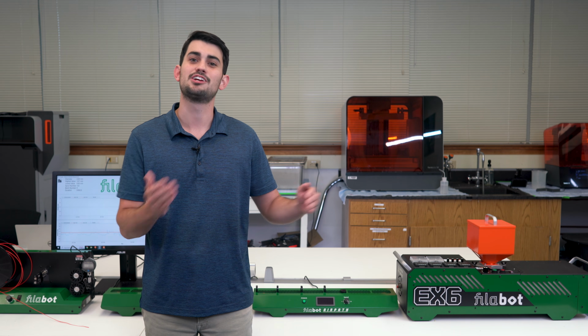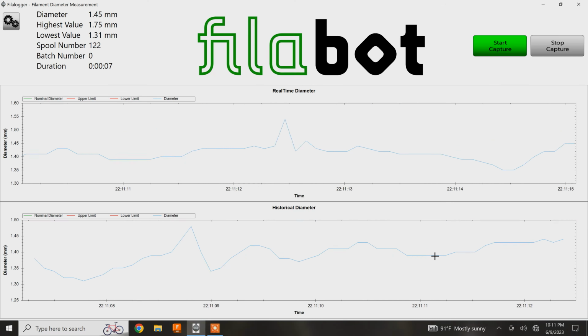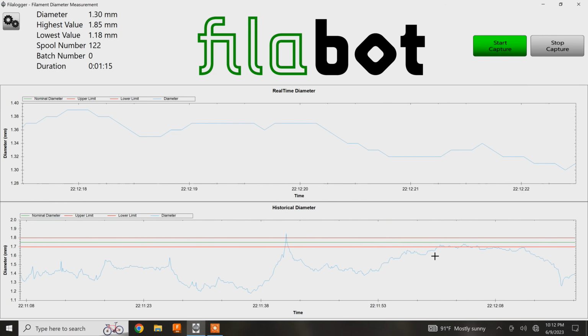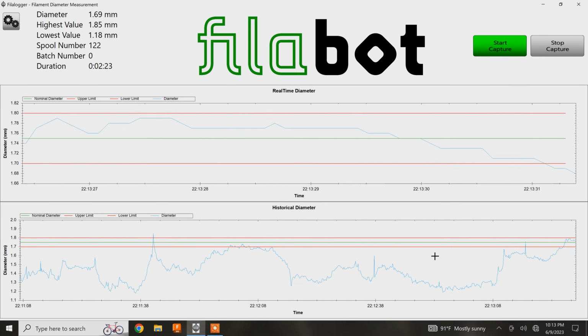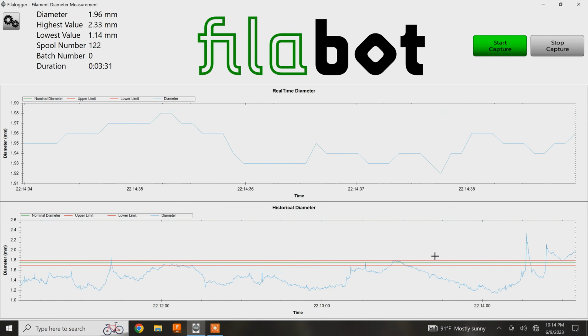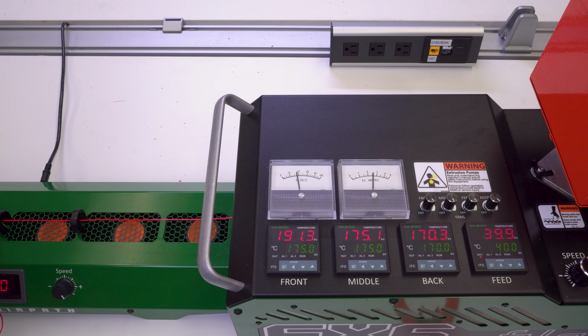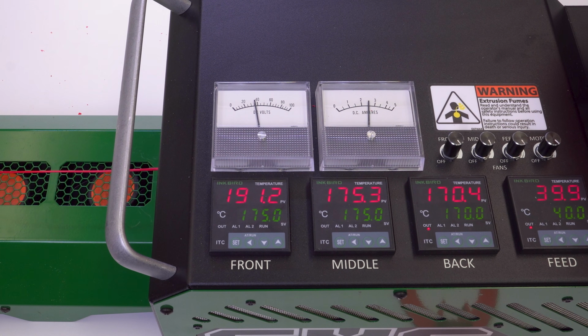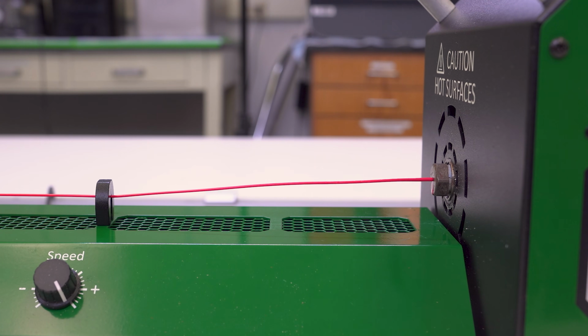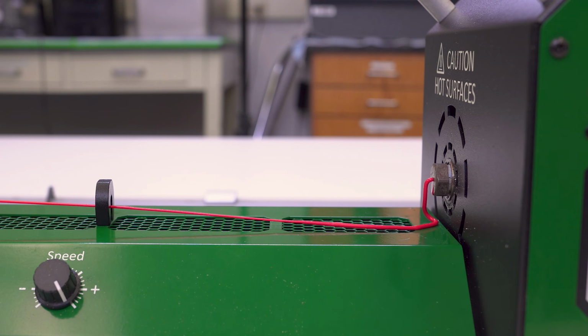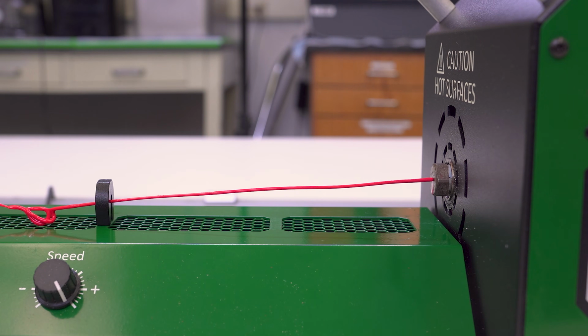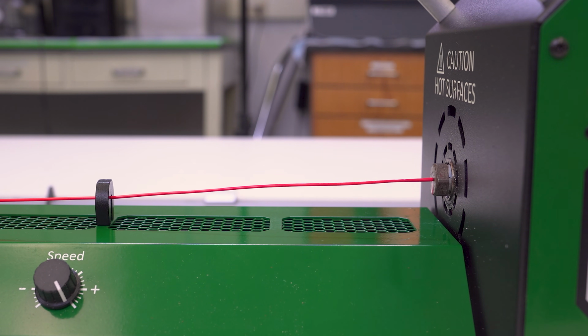As you might expect, increasing the amount of regrind to 50 weight percent increased the problems. I was not able to spool the filament because the output was swinging from 1 to 2 millimeters, but even more troublesome, the material was overheating and losing its shape due to a loss of its viscosity. If the filament is too soft, then it can't be pulled towards the spooler. Instead, it will pile up right next to the die. The combination of the motor consuming a lot of amps and there being a low output resulted in a small amount of material being exposed to significant viscous heating. Overheating will always be a concern when processing regrind.